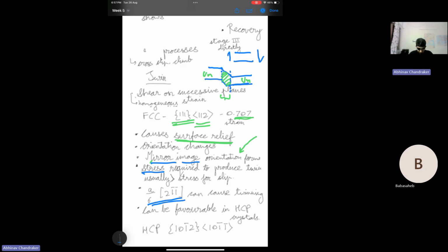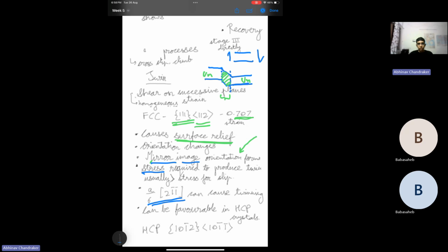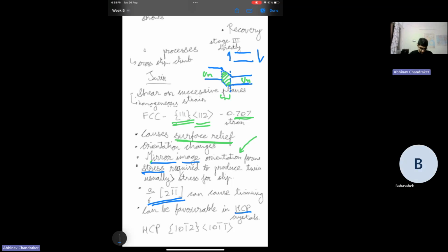And twinning has been seen to be more favorable, or more prevalent, in HCPs for plastic deformation, and a bigger cause of strain in HCPs. This is mainly because slip in HCP is comparatively difficult. Certain slip systems in HCP are efficient, others are inefficient. So depending on the loading geometry, it can happen that slip on those slip systems is difficult, and therefore it is much easier for twinning to occur. The stress required for twinning is comparatively lower. So in HCPs, twinning plays a bigger role in deformation.